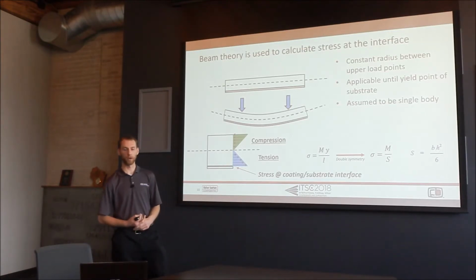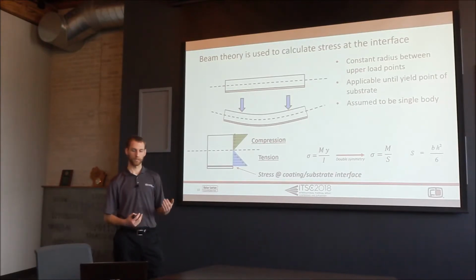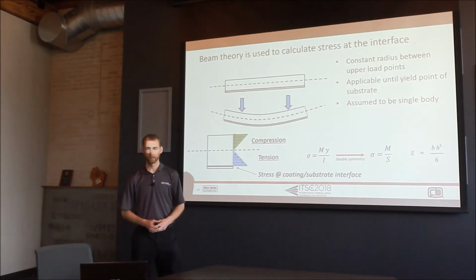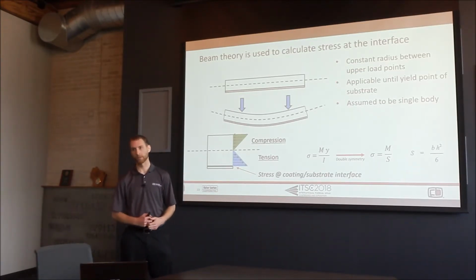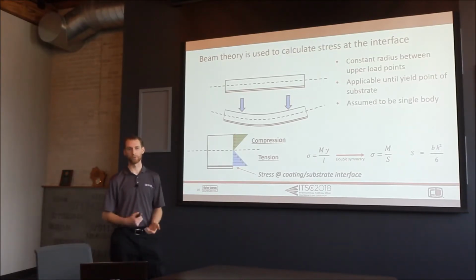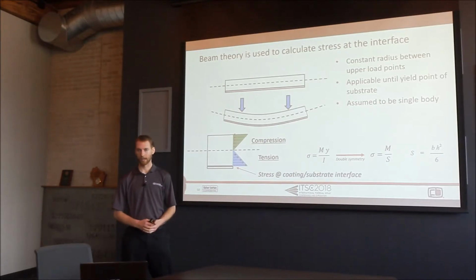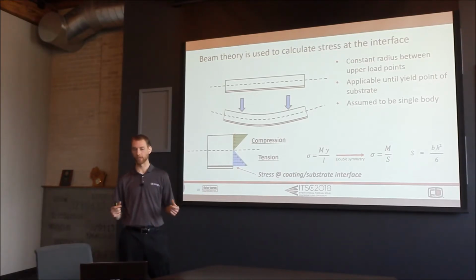Now, with our approach right now, we're assuming that it is a single body, and so basically the substrate properties dominate in this scenario. Beam theory is also only applicable until the yield point of the substrate, as far as the math goes, and I'll show that discontinuity when that yield point hits. The reason we use 4-point bend over 3-point bend is that there's a constant radius between the upper force components. That allows us more flexibility with our strain gauge positioning, and we have constant stress along that radius.